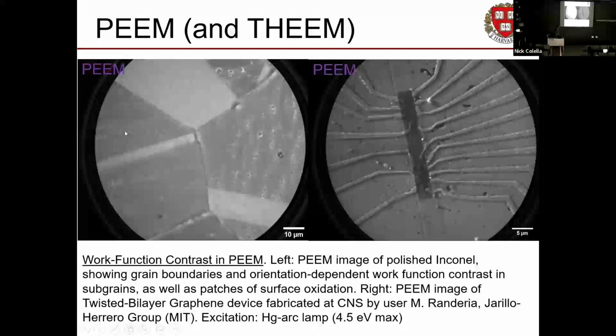These are different grains of metal in a piece of Inconel, which is a nickel alloy. And depending on the orientation of the crystal, the different facets of the crystal have different work functions. So you get these different contrasts. And you can see little pockets of oxide trying to grow on the surface of it here and here and here. This is a device made in the clean room.